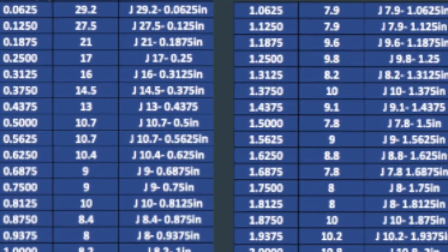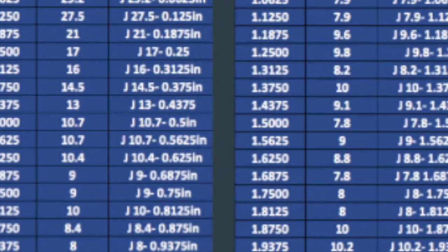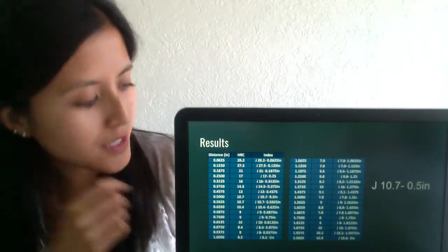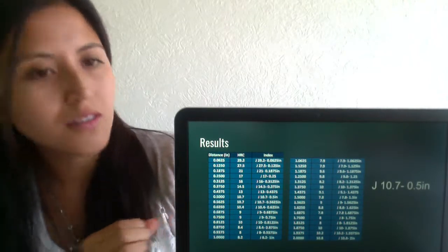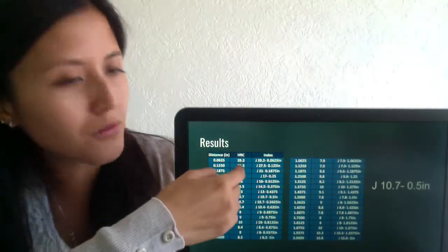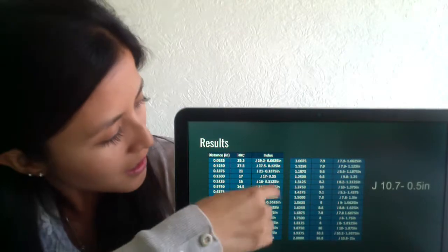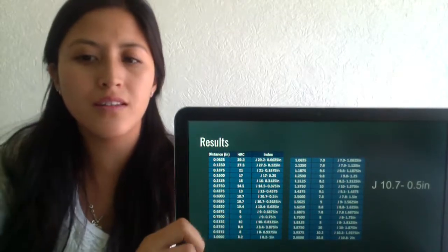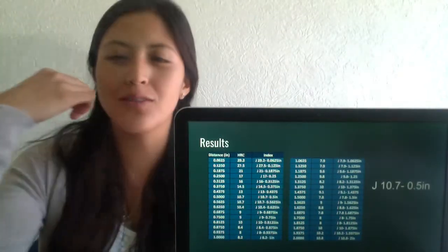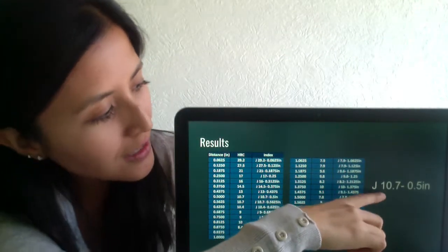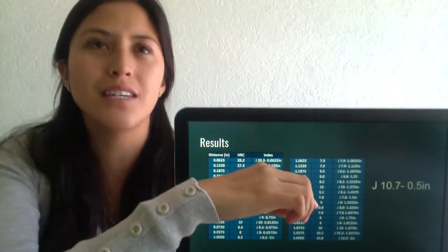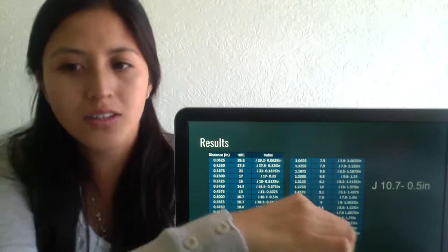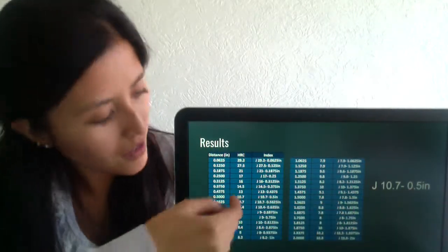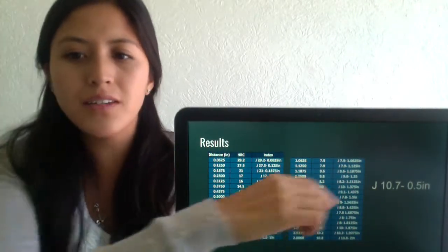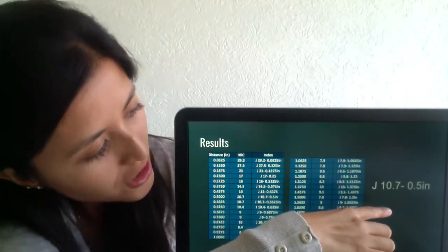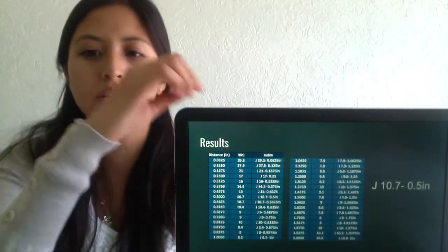On this slide we can see the indexes of the Jominy test. Here we have the distance from the quenched end and the Rockwell C hardness, and the index is formed with these two properties. First of all, we put a J, and this number represents the Rockwell C hardness, and this is the distance that we have here. For example, this is a distance of a half inch that has a hardness of 10.7 Rockwell C.